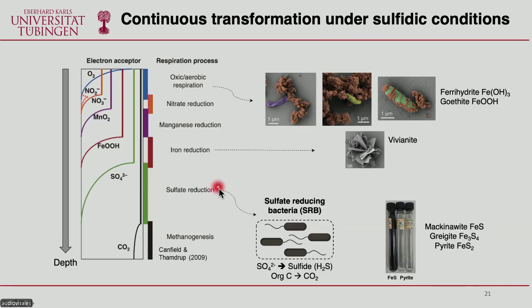But if they get buried even deeper, then we reach the zone of sulfate reduction. And in this zone of sulfate reduction, we have a lot of sulfate-reducing bacteria. They reduce sulfate to form hydrogen sulfide, coupled to the degradation of organic carbon, and then they form various types of iron sulfide minerals. Some of them have really weird names: mackinawite, greigite, and then pyrite, I think, is the one that's more commonly known.